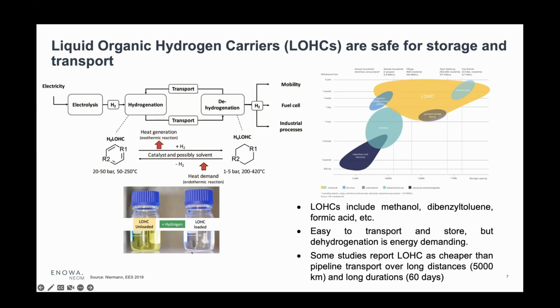The picture on the bottom shows you these types of LOHCs. They're liquids, they're clear. They might have a color when they're unloaded, and then when you add the hydrogen, they can change color because the material properties have changed. And then when you move that liquid to another destination, you add heat. It's an endothermic process, and you release the hydrogen and you regenerate your toluene or your LOHC carrier molecule. And then that hydrogen, which is removed from the LOHC, can be used for mobility applications, fuel cells, industrial processes. You can get a rather pure form of hydrogen.